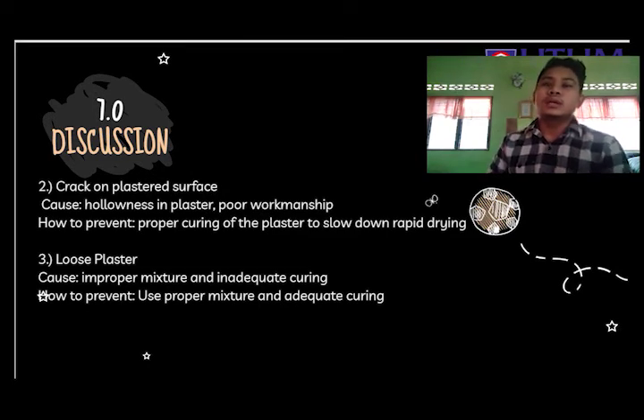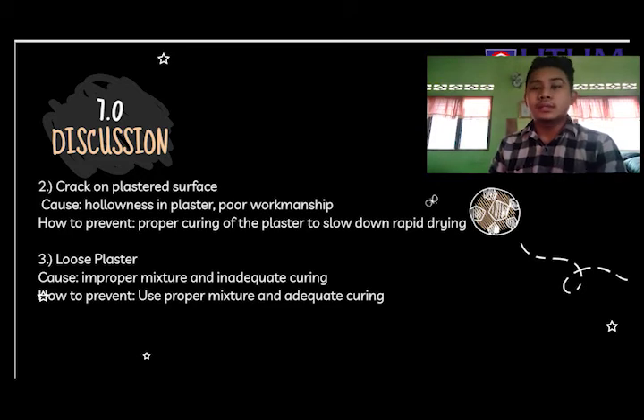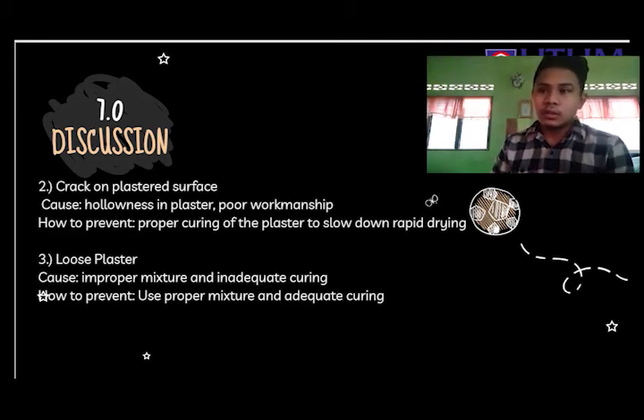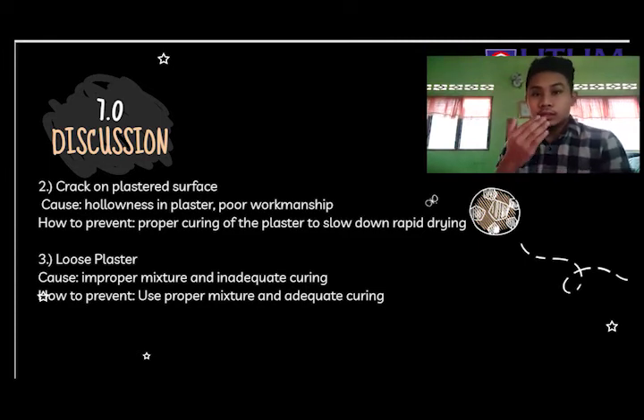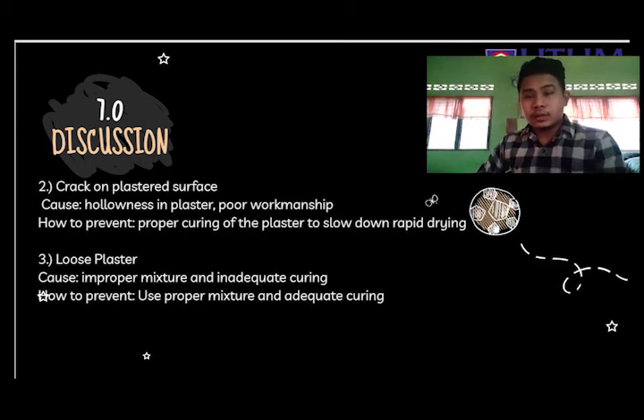Next, cracks on plaster surface. This is because of hollowness in plaster, or maybe poor workmanship. To prevent it, we need proper curing of the plaster to slow down the rapid drying. And last is loose plaster. This is because of improper mixture and inadequate curing, and it can be prevented by using proper mixture and adequate curing.